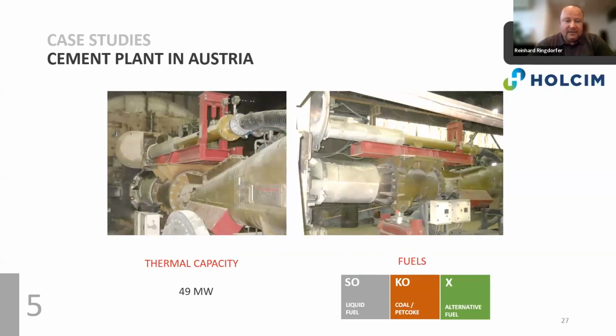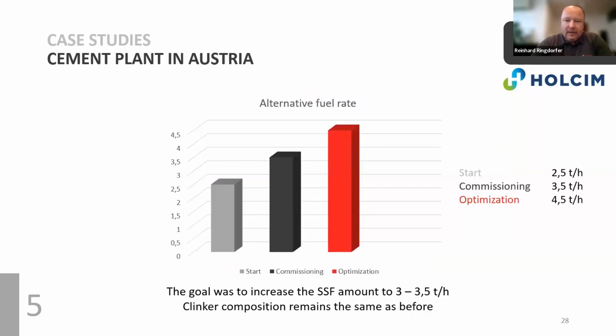Anyway, the capacity was 49 megawatts, or is 49 megawatts. Again, coal and petcoke, liquid fuel with alternative fuel. And we installed the satellite burner on top. And again, the start was at 2.5 tons per hour. Commissioning 3.5 tons, this was reached very quickly. And again, after optimization, we were able to reach 4.5 tons of substitution rate at the main burner.